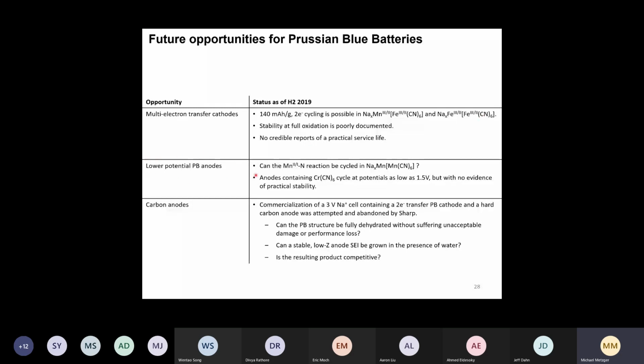Then the other thing, we learned that cell voltage is really very important in these cells because you don't have a large operating voltage, a large voltage difference between anode and cathode in most cases. But what would be really nice is if you could access this even lower voltage manganese 2+/1+ redox that is associated with the manganese that is bound to the nitrogen. So we talked about the manganese 2+/1+ redox of the manganese that is bound to the CN6 groups. That would be at a lower voltage, and in this cathode that Natron already uses, the question is, can you cycle this reversibly if you have the right electrolyte and all these things?